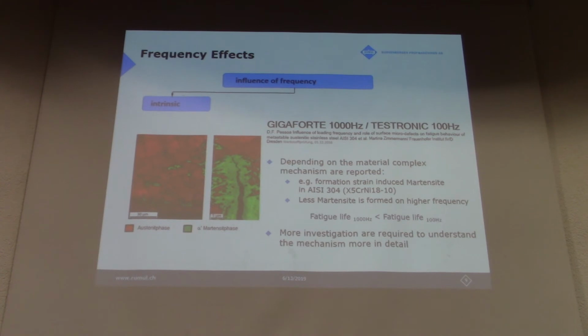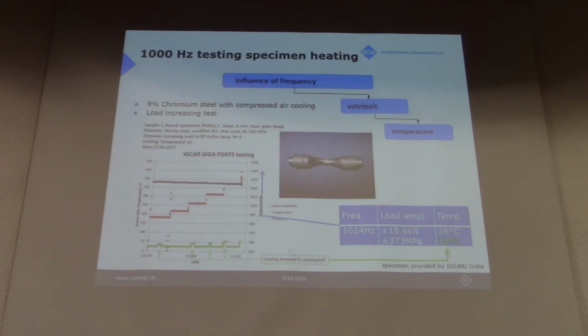Here is another very interesting work, in my point of view, where Mr. Passoa at the Fraunhofer Institute in Dresden found some surprising results, that the fatigue life at higher testing frequency is less, and this could be correlated with the formation of strain-induced martensite. It seems to also be related to the testing frequency. But the most significant effect is probably the heating up of the sample.